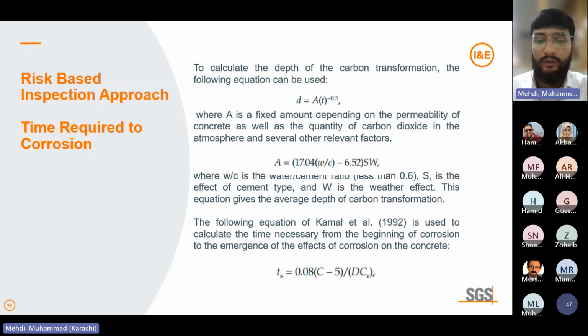It is also important to consider that in the case of structures exposed to carbonation, it spreads inside the concrete cover, and several equations can be used to calculate the time required for this propagation. To calculate the depth of the carbonation, the equation is D equals A into T power negative 0.5. This equation can be used to calculate the depth of the carbonation, where A is a fixed amount depending on the permeability of the concrete as well as the quantity of carbon dioxide in the atmosphere. And there are several further factors.